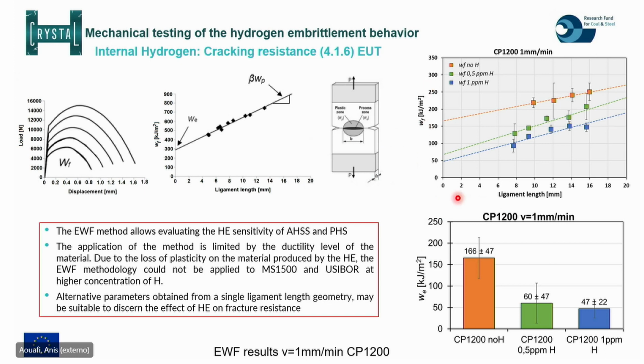What is shown here on the left, on the top, is the total work of fracture that has been obtained with different hydrogen content. And as you can see here, for different ligaments, we can highlight that using this kind of test, essential work of fracture, we can discriminate the effect of hydrogen and the effect of different contents of hydrogen using the total work of fracture as a parameter. We have the same conclusion regarding the essential work of fracture, and as you can see, the essential work of fracture drops when the hydrogen content increases in the specimen. So here I show you the good results that have been obtained using this kind of methodology for CP1200.